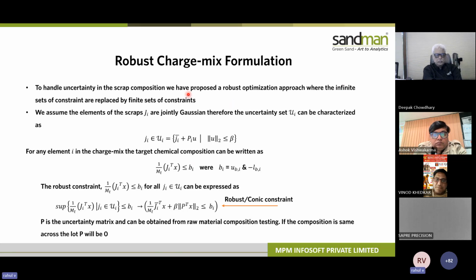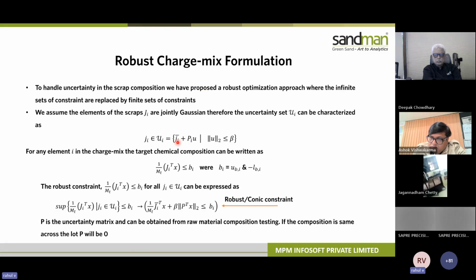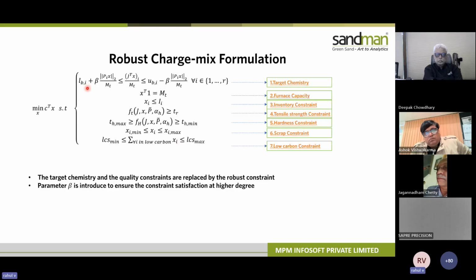So what we decided is we'll solve this problem by handling this uncertainty with a robust charge mix formulation. We model the uncertainty as a P matrix. It's a big technical term, but basically this P matrix is just to represent the uncertainty. And we are saying that this new chemistry, J plus PU, will be my final chemistry. So the robust charge mix translates into this. Still the target chemistry, furnace capacity constraint, inventory constraint, tensile strength, hardness, scrap constraint, and low carbon constraint are all met, while handling uncertainty in the target chemistry as well as in the mechanical properties like tensile and hardness.